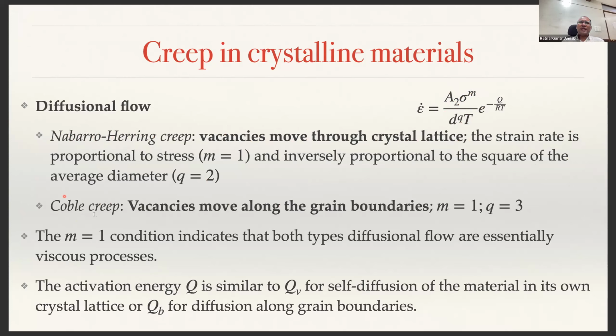There is another creep mechanism called Coble creep, where m is equal to 1, q equal to 3. Depending upon the material, I'm not going to go into the details of when Nabarro-Herring creep or Coble creep is more dominant. But when you know that the mechanism is better described by Coble creep than Nabarro-Herring creep, then you have to take q equal to 3. And again, the activation energy Q is very similar to the activation energy for self-diffusion in the crystal lattice, or Q_B for diffusion along the grain boundaries.